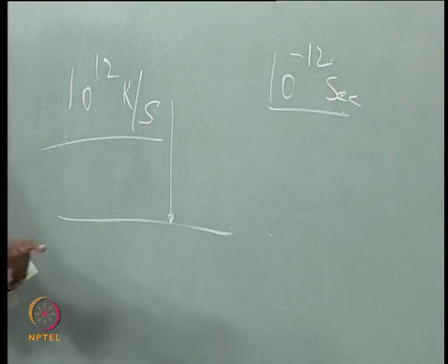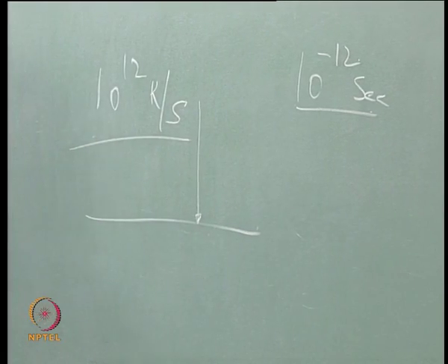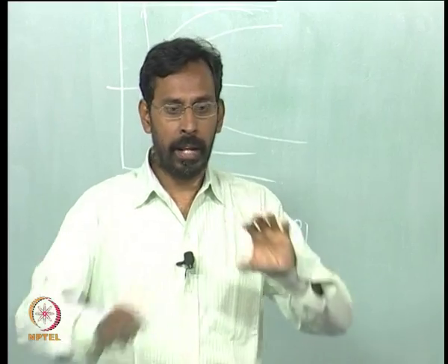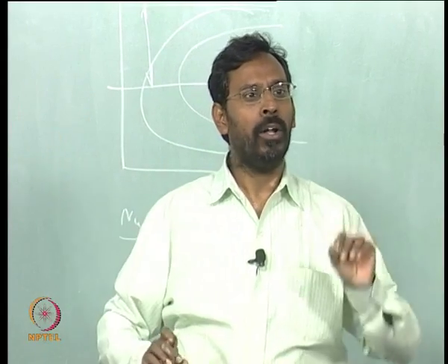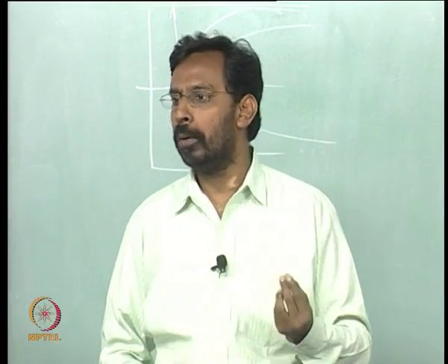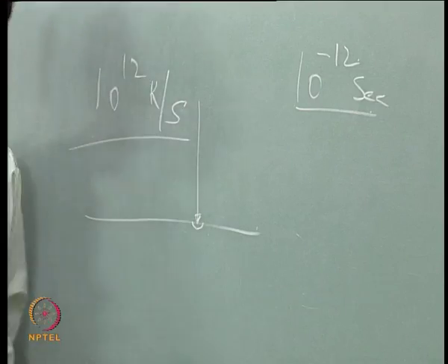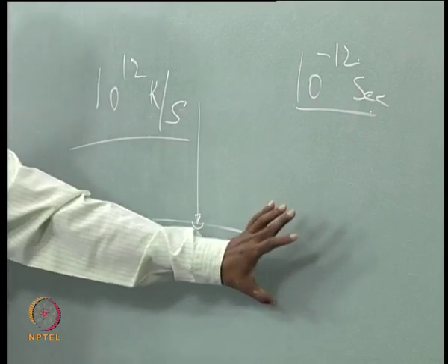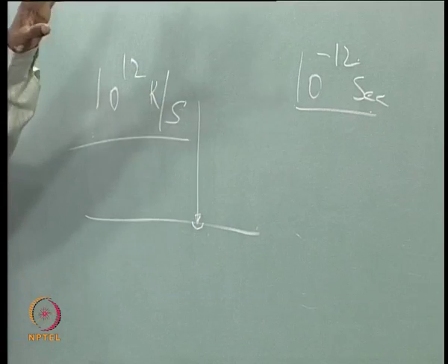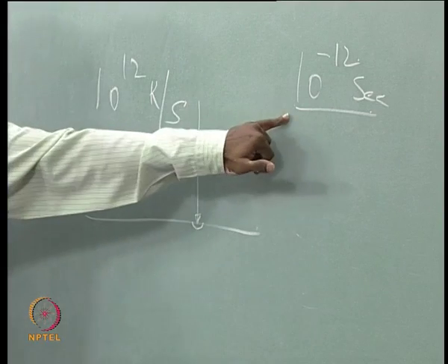Then within that period it has to cool back, and how does it cool? The whole metal itself acts as a quenchant. In a slab of metal, only a few cubic micrometers of a region is actually melted, a small pool. So the rest of the metal quenches that liquid. So you get the liquid brought back from 1000 degrees to room temperature within this particular period.